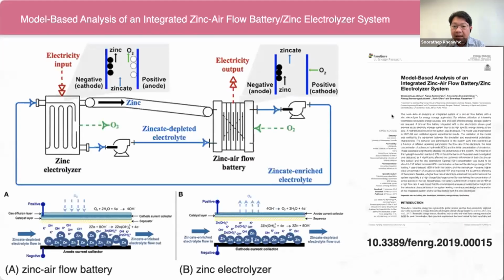To evaluate the performance of such a system, which integrates zinc-air flow batteries and a zinc electrolyzer, we developed a mathematical model. The following parameters were investigated: electrolyte flow rate, potassium hydroxide concentration, and zinc cation concentration. Besides, the influence of the hydrogen evolution reaction on the performance of the system was examined. Upon investigation, it was found that potassium hydroxide concentration had a significant effect on the performance of the battery. Further, it was noted that increasing potassium hydroxide concentration enhanced HER, the hydrogen evolution reaction, and reduced the current efficiency. However, the optimum potassium hydroxide concentration, about 7 molar, provided maximum energy.